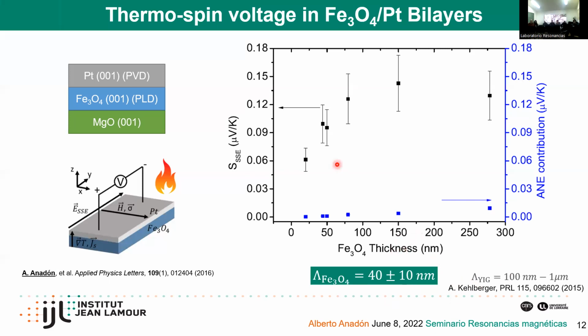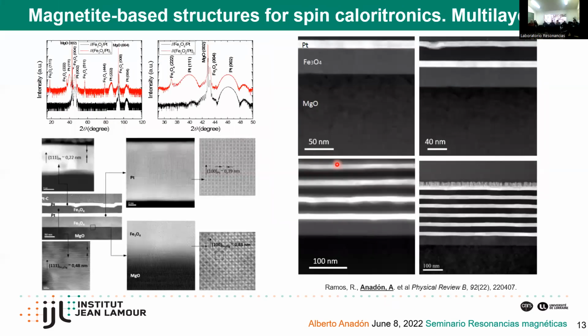And so we move then to more complex systems, and we were able to prepare different multilayers with several magnetite-platinum repetitions. So we prepared also this using the same combination of pulsed laser deposition with sputtering. As you can see, also the quality of the system is very high. When the number of repetitions increases, it's possible to see that there's some relaxation of the material. So the system is not as crystalline as it is in the first layers, but still the layers hold quite well, as you can see in this TEM image.